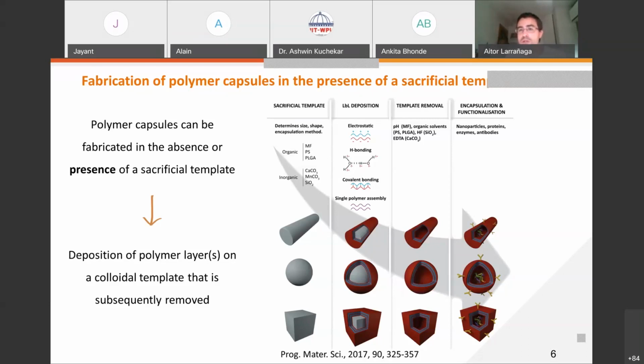So for example, if we use a polymeric nano or microparticle as a sacrificial template, such as polystyrene nanoparticles, we could use an organic solvent to remove the sacrificial template. In case we use, for example, silica nanoparticles as a sacrificial template, we could use hydrofluoric acid. Or in case we use calcium carbonate as a sacrificial template, we could use a calcium chelating agent such as EDTA to remove the sacrificial template.